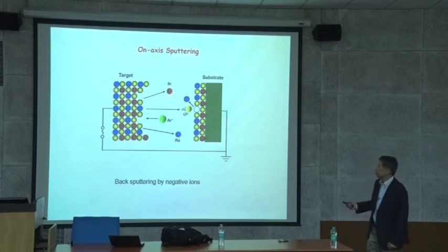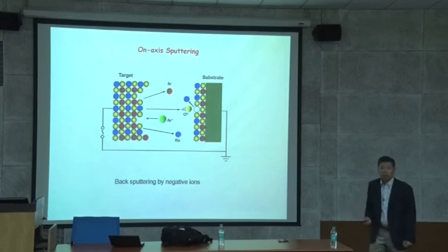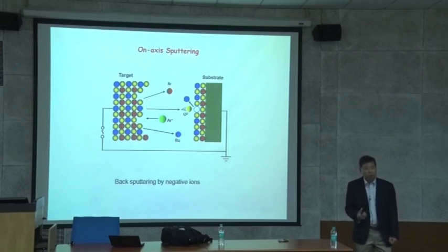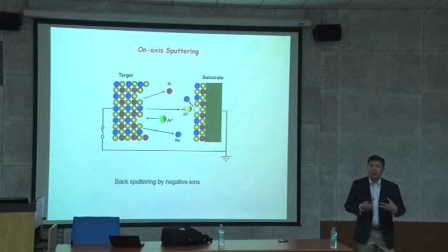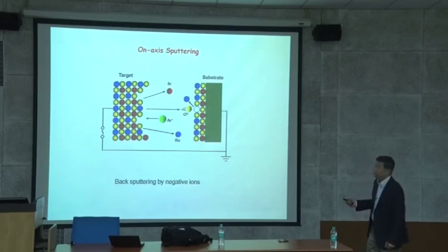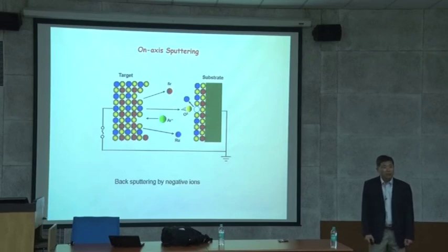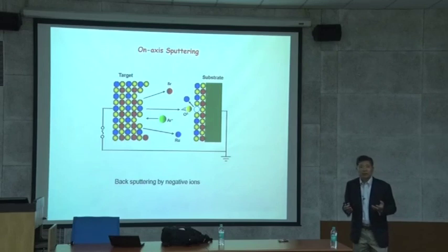And the problem is, when you sputter, not just this metal, strontium and ruthenium, is either neutral, or you have ions. You can have both come out, okay? Because when you sputter, when you break the bond, it can be ions or it can be neutral. And the ions can easily be combined with electrons and become neutral. But look at this, oxygen also comes out from the target, because the ceramic target contains oxygen. But when the oxygen comes out, it is an O minus two ion.